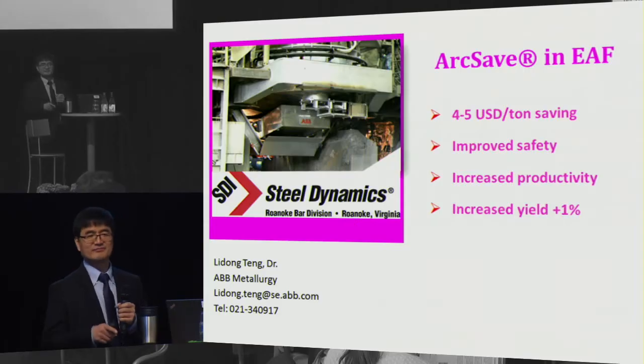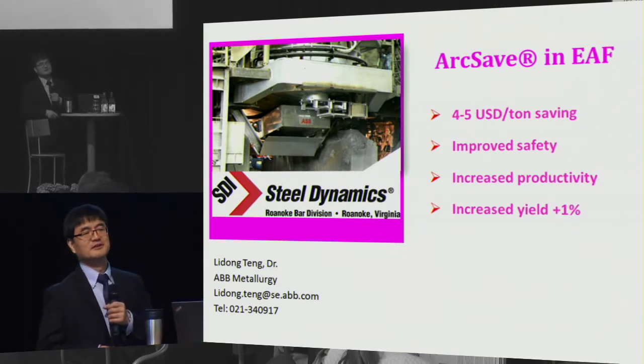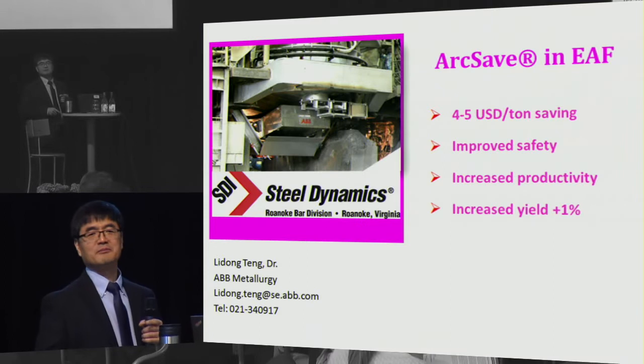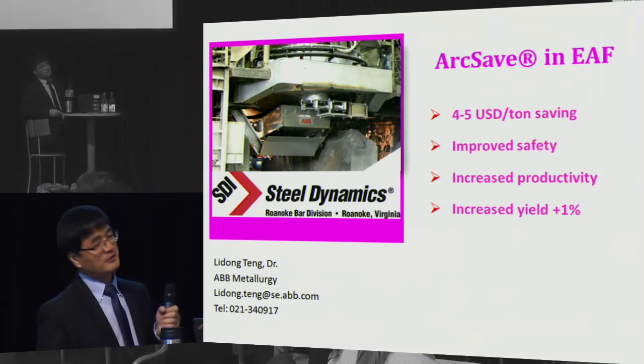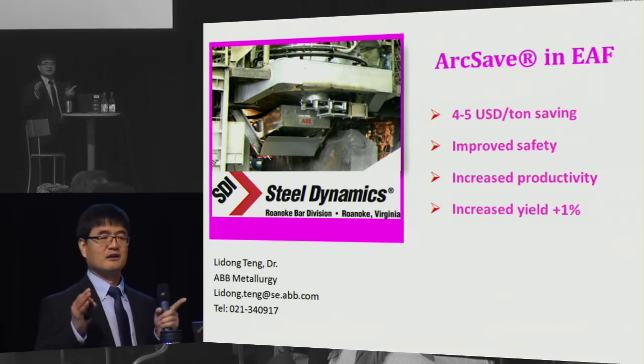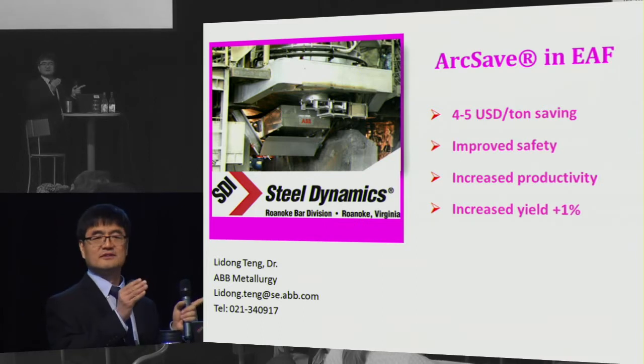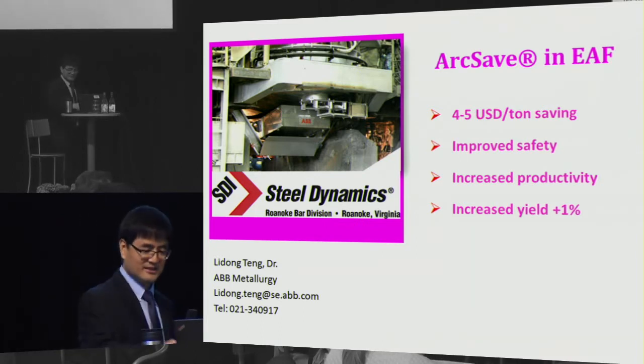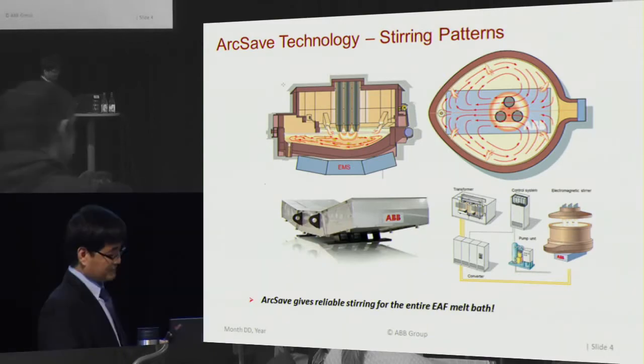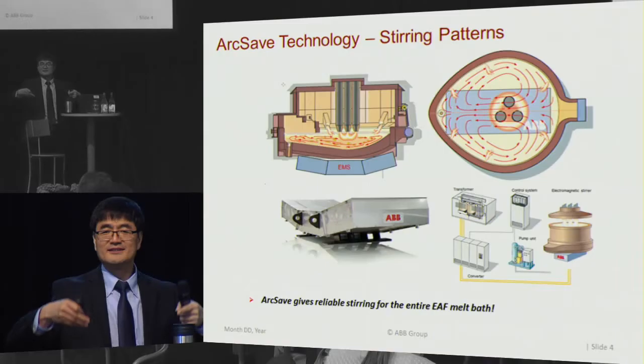ArcSave is a magnetic stirring for the arc furnace, like overall stirring. We had that old product some years back. Now we have developed a new generation which has a little bit higher force and directs the melt like that. Then the melt in the furnace could move in this way or turn back.